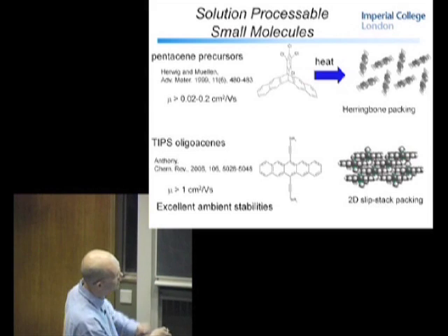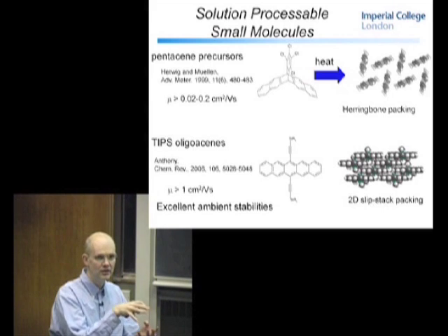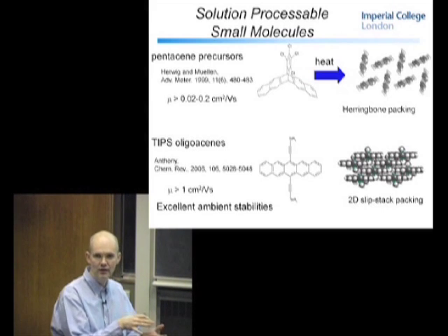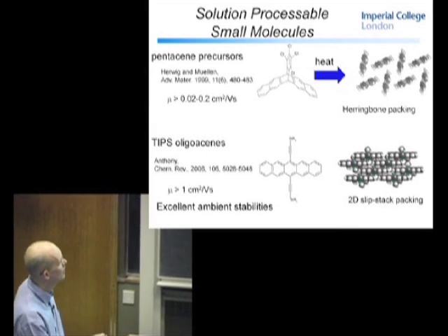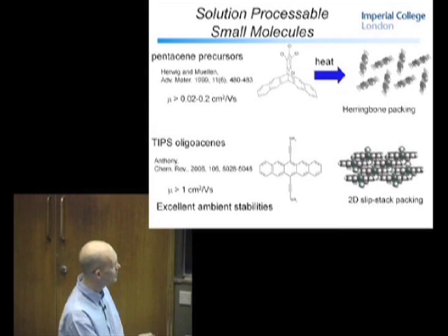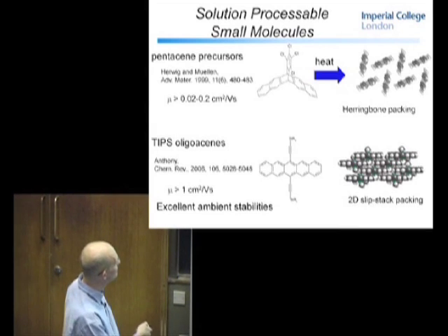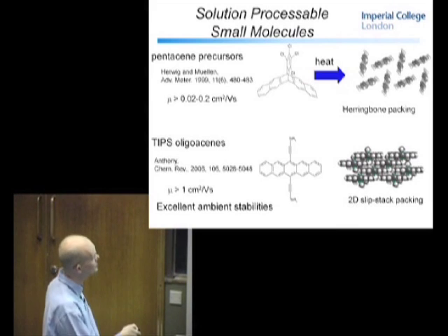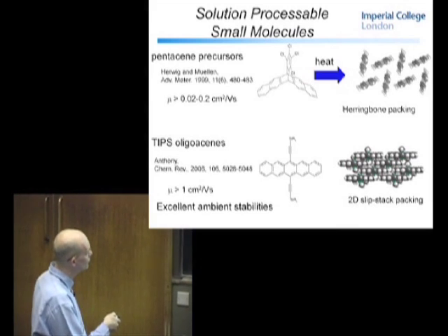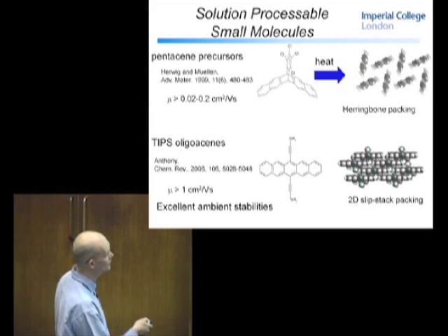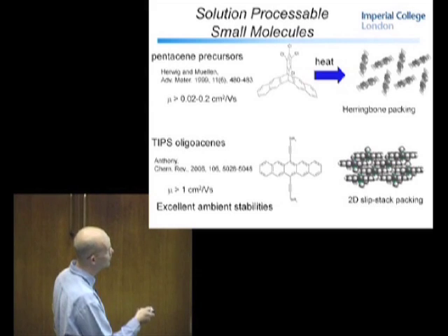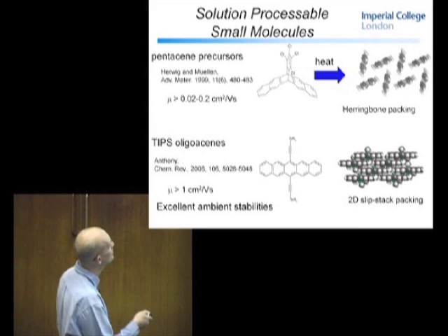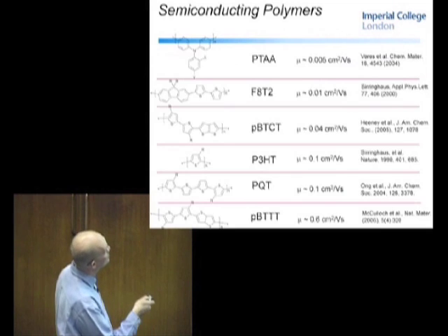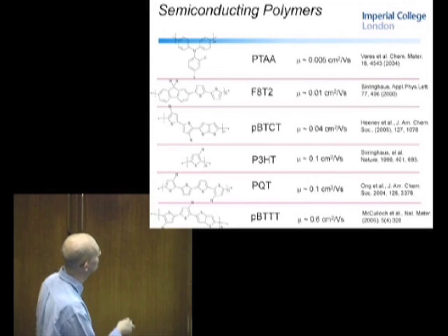This is one acene, this is another. So the side units actually dictate the crystallization and the packing in an optimum way. And this way you get a very nice packing for transport, and mobility is really very high. In fact, I've seen mobilities of over 5 with a different oligoacene, which we've been working on at Merck and other places. In terms of semiconducting polymers, there's a whole range of polymers.